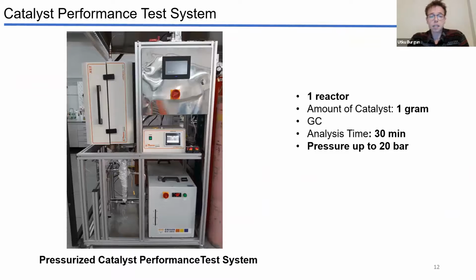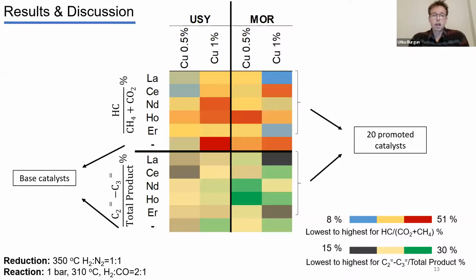The other performance test system is the pressurized test system. In this test system, there is 1 reactor, and it requires 1 gram of catalyst. The analysis is provided by a conventional GC, the analysis time is 30 minutes, and here pressure can be increased up to 20 bar. Before the reaction, all catalysts were reduced under hydrogen flow at 350 degrees Celsius, and then the reaction occurred at 310 degrees Celsius with a flow of hydrogen over carbon monoxide.